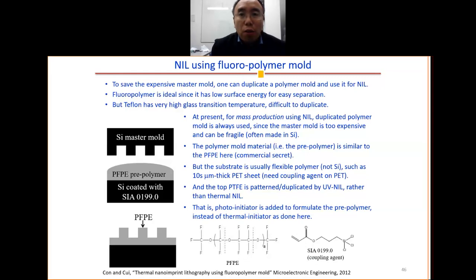So this is the fluoropolymer mold. We know that normally the master mold is very difficult and expensive to make. So to save the master mold, we can copy the master mold into a polymer mold. Then we use the polymer mold to do the imprint. The good polymer is the fluorocarbon polymer. This polymer is good because it has a very low surface energy, for easy separation. But Teflon is not very good, and we will see later on it is difficult to copy the mold into Teflon. But fluorocarbon, the other fluoropolymer, is good.